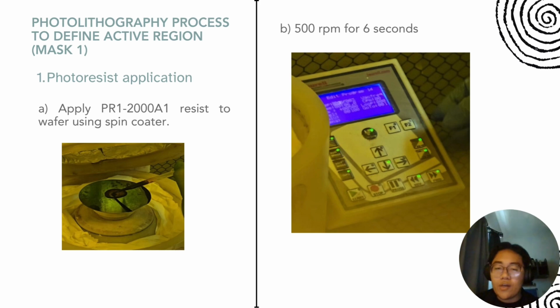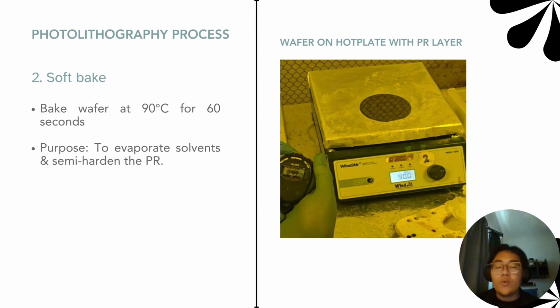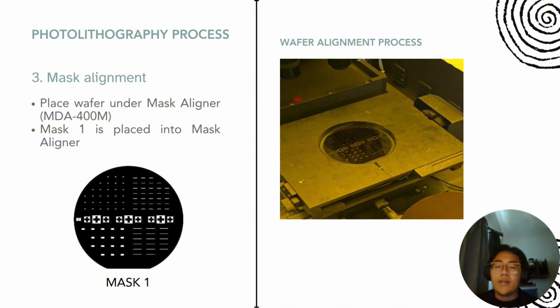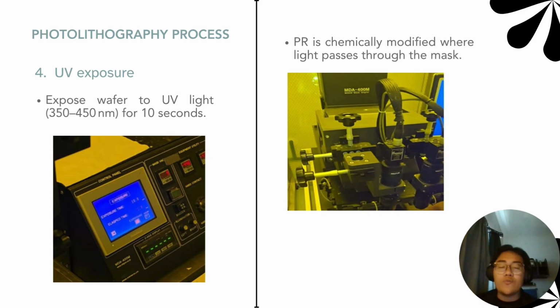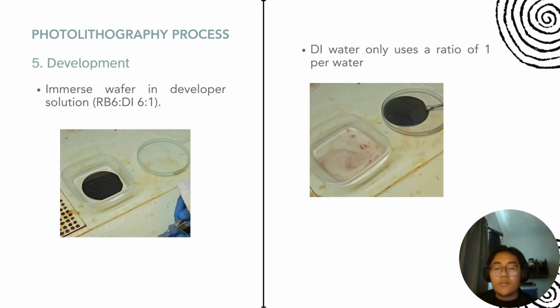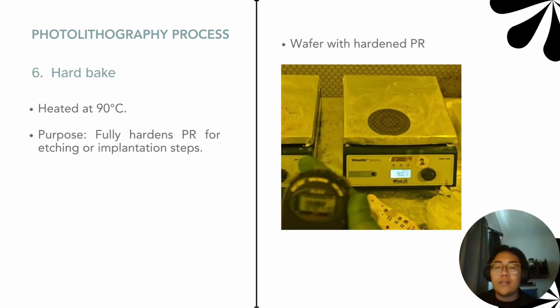For the photolithography process, we define the active region using mask 1. We apply the photoresist on the wafer and then spin coat it at 500 RPM for 6 seconds. And then we do a soft bake. We soft bake it at 90 degrees Celsius for 60 seconds in order to semi-harden the photoresist. Then we align the wafer with mask 1 before we expose. We expose the wafer using UV light for 10 seconds. After exposure, we develop the wafer in the developer solution.